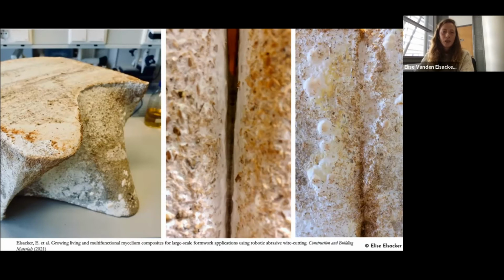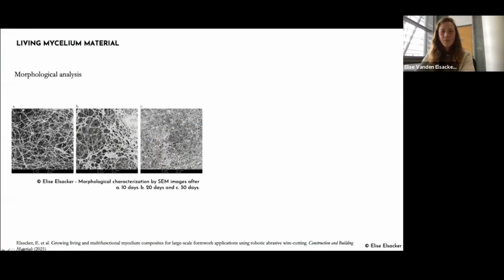Of course, there are many challenges to keep mycelium alive. For example, in the right image, you can see a little bit that the organism starts to differentiate to create fruiting bodies. Obviously, we don't really want this in building materials. So as the organism continued to grow, it also produced a denser network. You can see on the right image, after 30 days, this is a microscopical image, it has a much denser mycelium network.